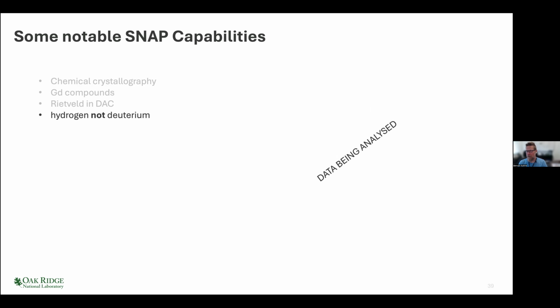So unfortunately, I can't say what it is right now, but we've been looking at very hydrogen-rich samples, more than 50% hydrogen, and it seems entirely tractable. So we're super excited about this because A, it's often not possible to deuterate your sample, and B, quite often the physics is different if you're using hydrogen instead of deuterium. So that's something we're very excited about.